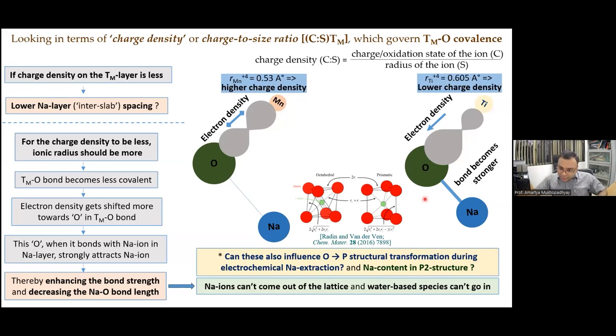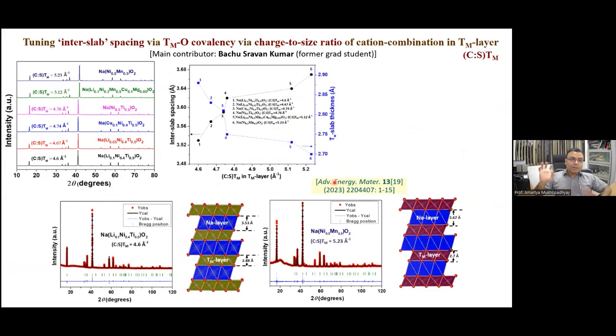Now, the effective negative charge on the oxygen ion may also render the octahedral versus prismatic coordination more or less stable. We can tune the stability of the octahedral versus prismatic coordination, and that is what we will see towards the later half of the talk. Now, coming to the air-water stability, we designed model layered transition metal oxide cathode materials by varying the charge to size ratio, as I have talked about in the previous slide.